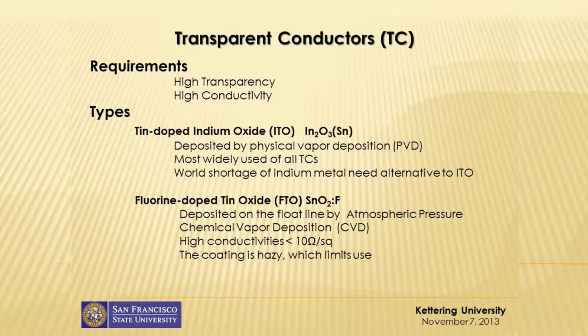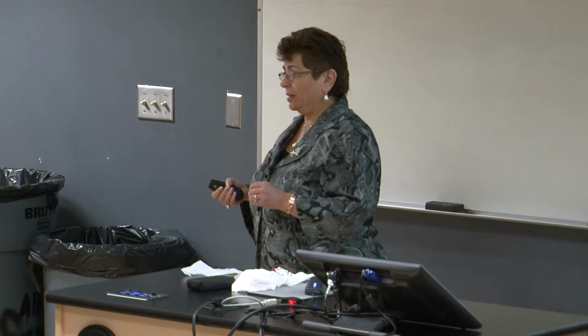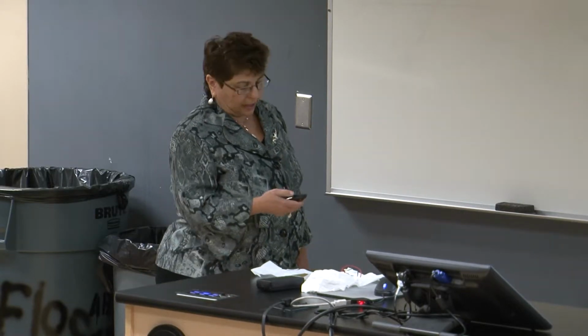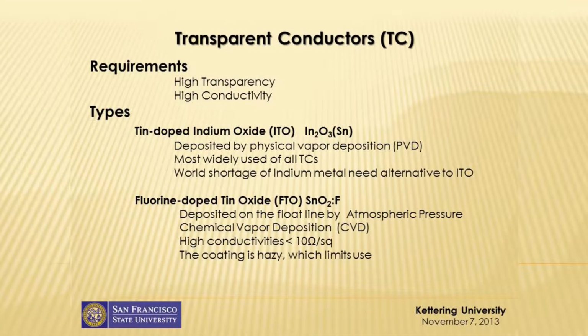With the shortage of indium metal, we need to find an alternative material replacing ITO. And then they found the fluorine-doped tin oxide films, which we call FTO, another inorganic material. FTO is deposited by the float line by atmospheric pressure chemical vapor deposition, CVD, and it has high conductivity, which is less than 10 ohm per square.